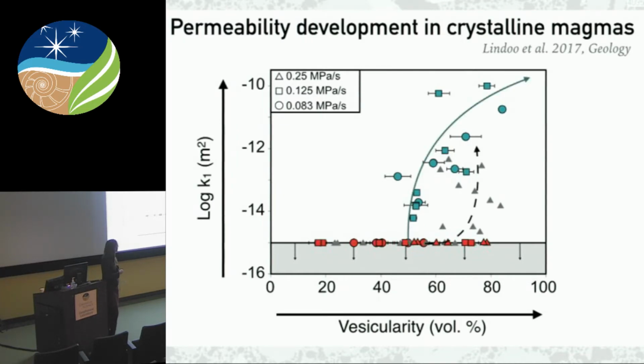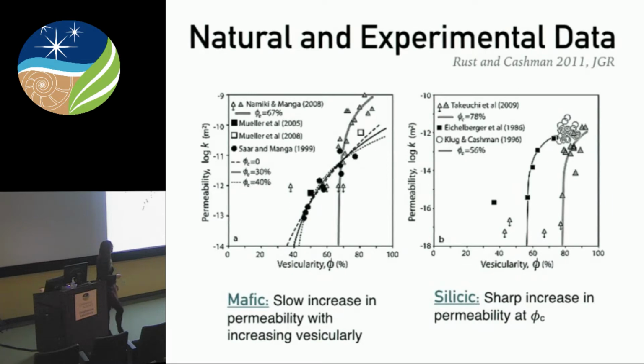And along with this, we also see this in nature, in that silicic pyroclasts tend to experience a sharp increase in permeability at the percolation threshold, and in mafic pyroclasts, we see this gradual trend in the permeability vesicularity relationship. And this straight up and down line right here is the analog study that I referred to earlier. It's the crystal freeze study that suggests mafic magma should have high percolation thresholds.